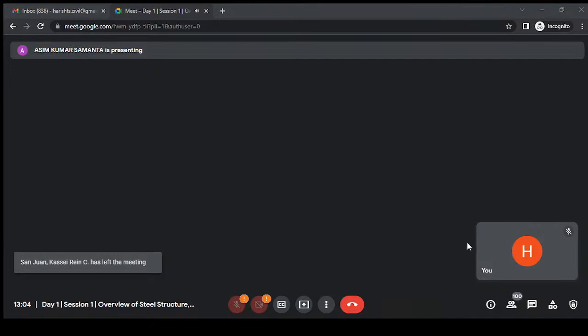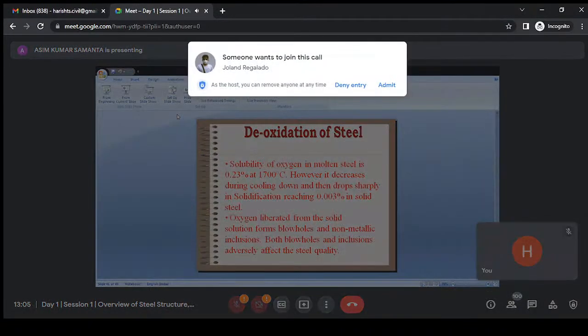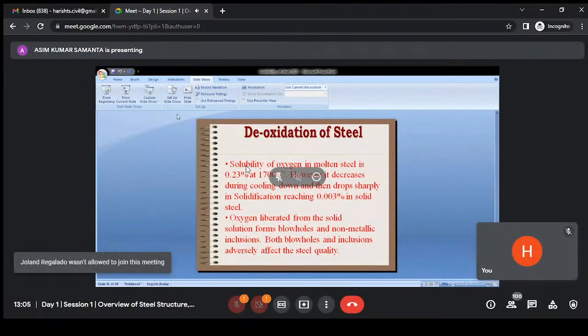Then the deoxidation of steel. In the steel manufacturing process, iron ore is put in the blast furnace, then in the steel melting shop, and then steel is produced. In the blast furnace, pig iron is made. When going from iron to steel, refinement takes place, oxygen lancing is done, and the liquid steel absorbs oxygen. Now, when solidification of the steel takes place, the solubility of oxygen comes down heavily: in liquid condition it is around 0.23%, while in cold condition it is 0.003%.